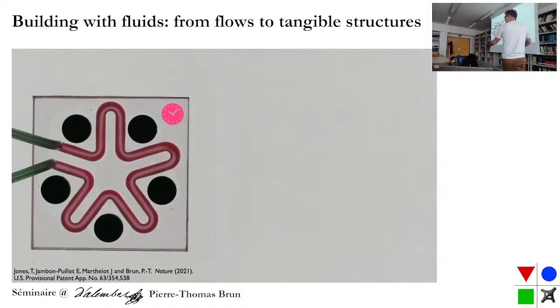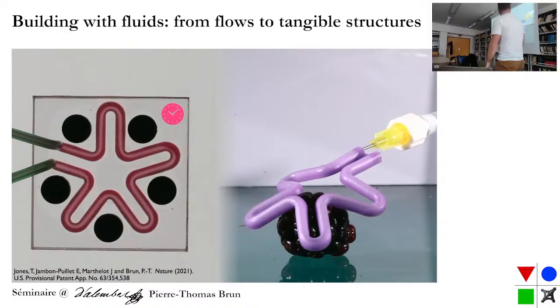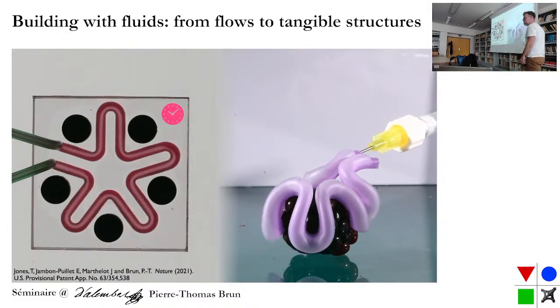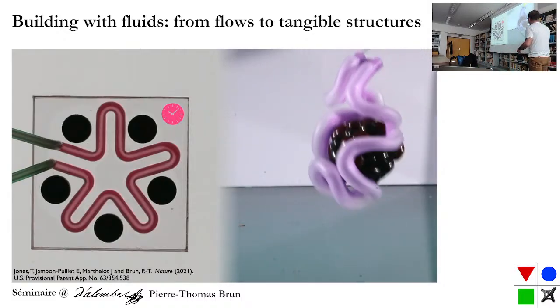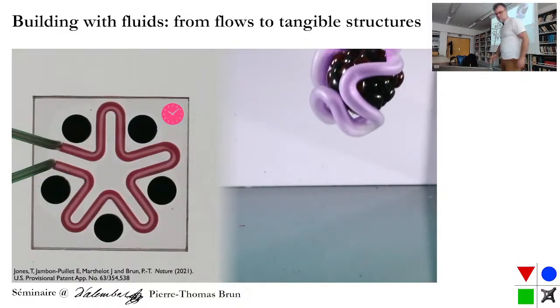Then you wait for 10 minutes. And during the 10 minutes, 2 things will happen. Gravity points this way, so whatever you've been coating, your cylinder will drain. And then this thing will cure. And so once you're done, you can take it away. And you inflate it, because that's a balloon. So what you do with balloons, you inflate them. And you have something that looks like a gripper, a soft robotic gripper.